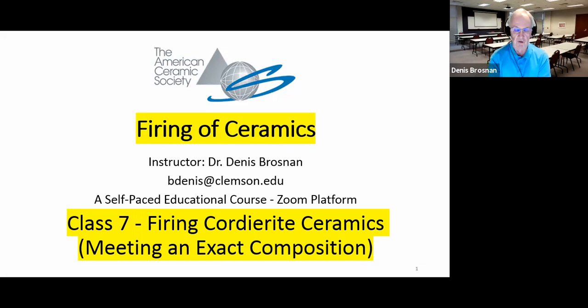Before I get started, I want to say that we've explored the basic information from within the material that tells us what to do during firing. A while back, we started out with vitrified ceramics, and we learned that we just basically need to get temperature to activate the fluxes, create the glass, and soak long enough for enough glass to be formed for the ceramic to have the strength and the absorption characteristics that it needs to have.